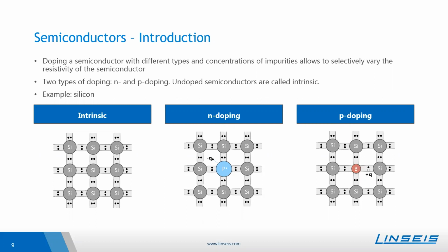For the case of N-doping, one replaces one atom on the regular lattice site with an atom of a higher valence. For example, in the case of silicon, one can use phosphorus. The phosphorus atom doping leads to additional electrons in the conduction band. So here it is schematically shown that there will be some further electron.